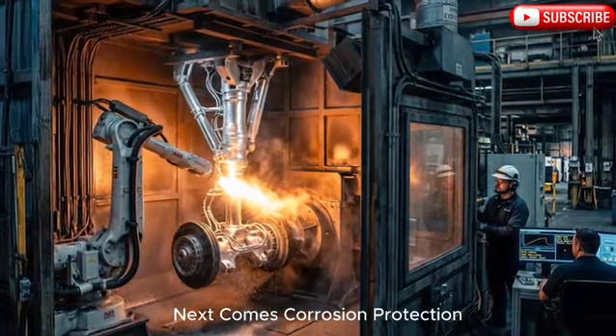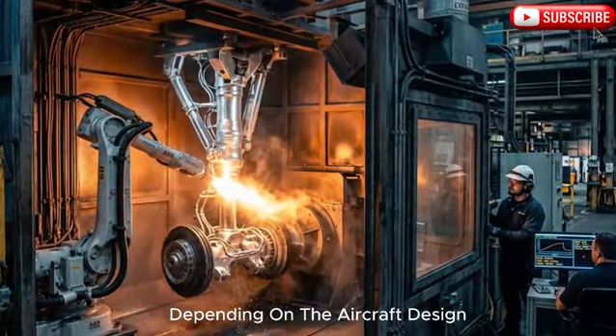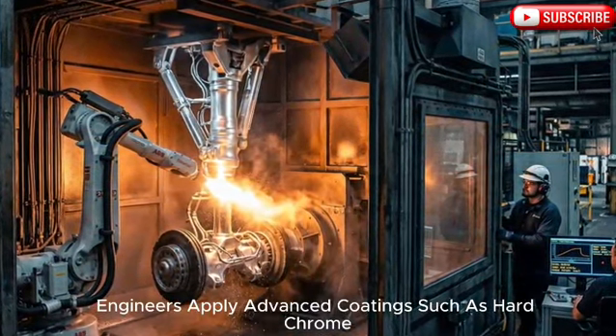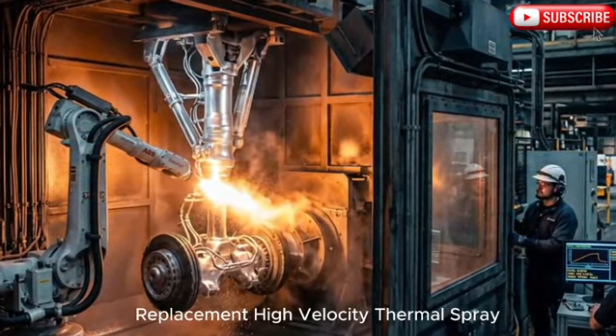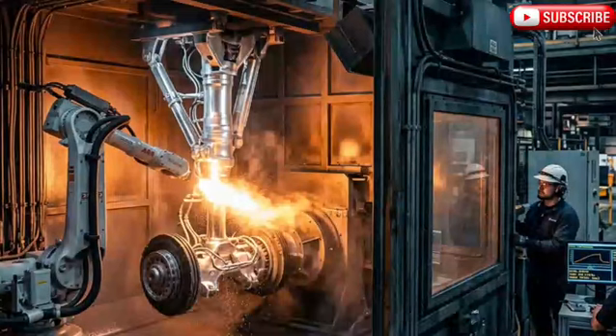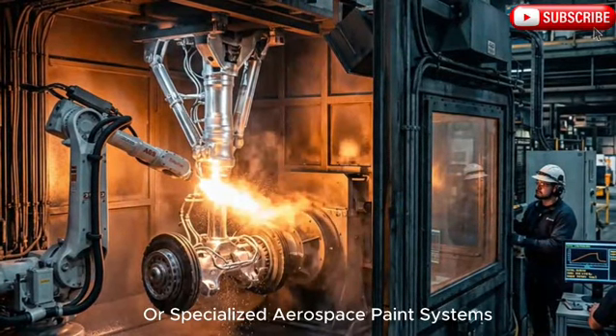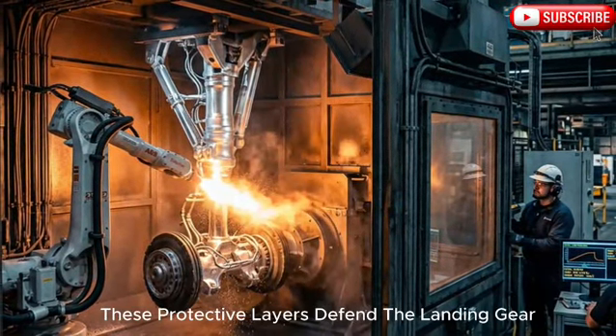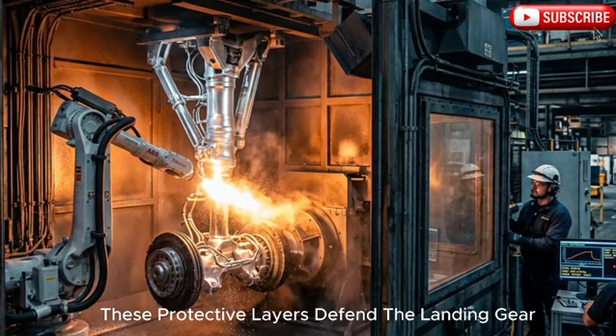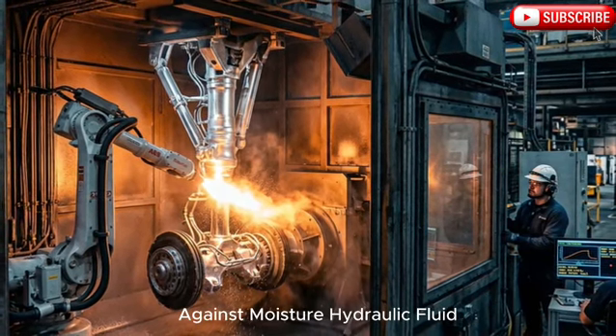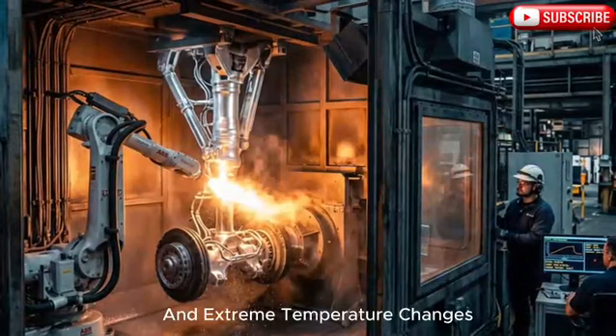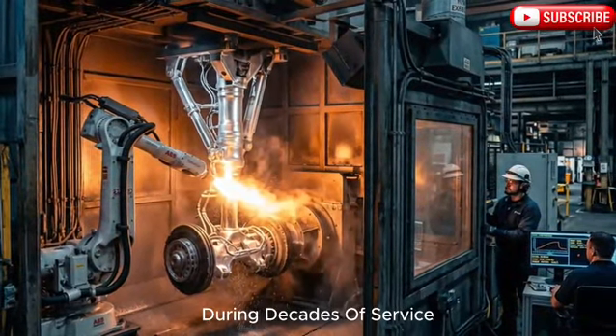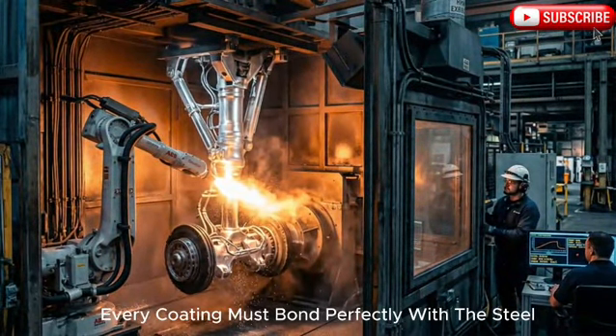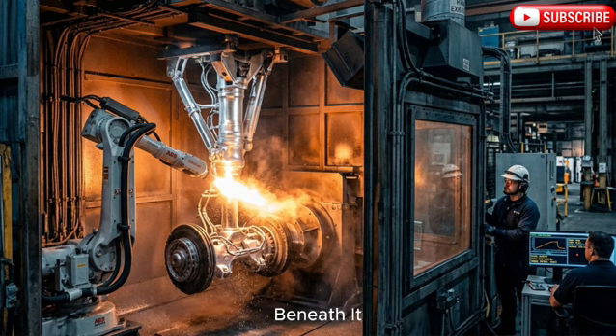Next comes corrosion protection. Depending on the aircraft design, engineers apply advanced coatings such as hard chrome replacement, high-velocity thermal spray, or specialized aerospace paint systems only a few microns thick. These protective layers defend the landing gear against moisture, hydraulic fluid, salt, ice, and extreme temperature changes during decades of service. Every coating must bond perfectly with the steel beneath it.